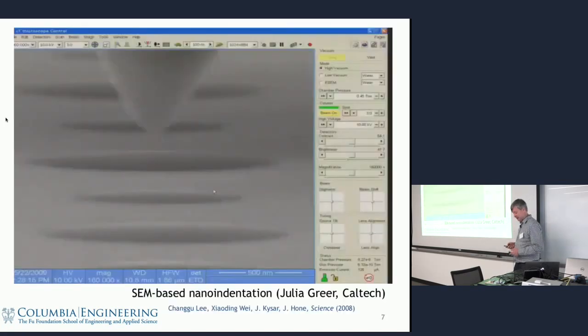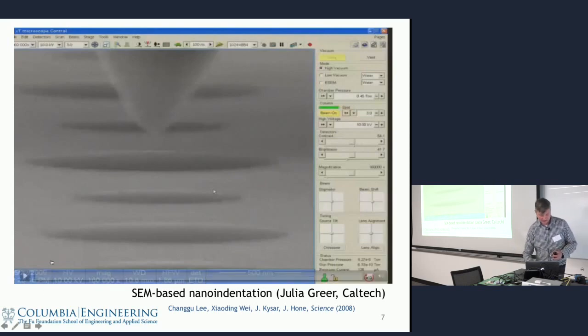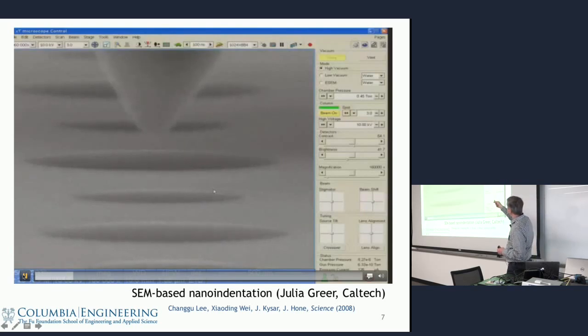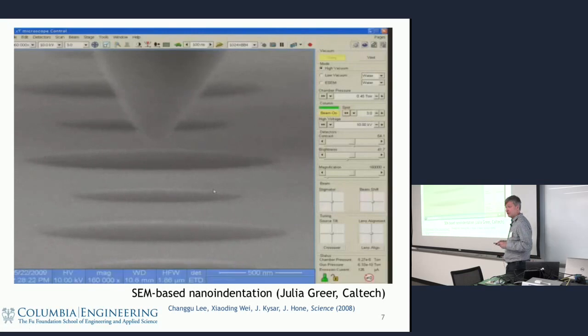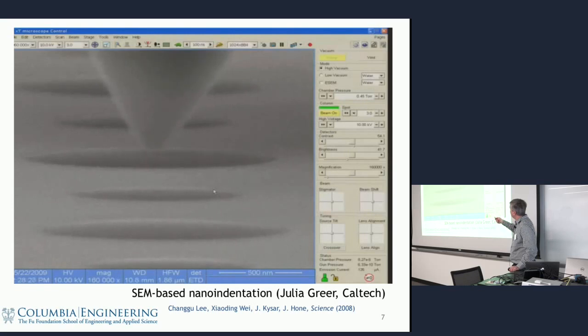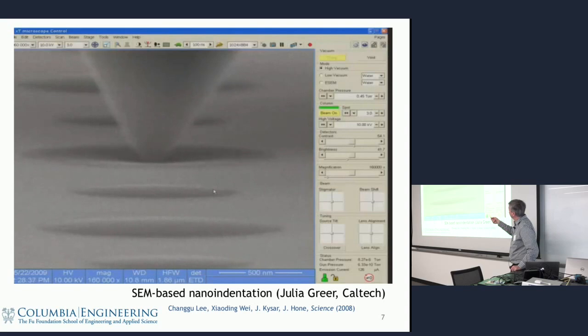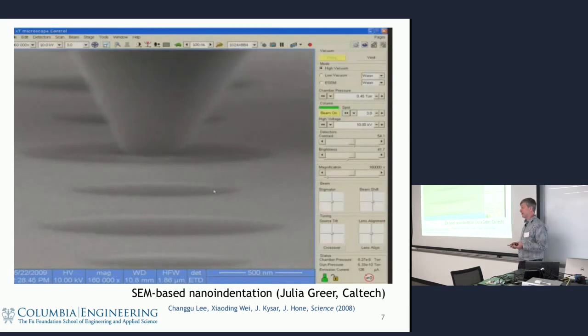So when we do these indentation tests, we get something that looks like this. So this is actually, we don't have a nice system like this. This is our friend Julia Greer at Caltech did this movie. But the idea is we come in with a tip. So this is a diamond tip. I'll talk about in the original experiments, we first started with conventional tips. This is some of these membranes, 1 and 1.5 micron in diameter, looked at from an angle, which is why they look elliptical. And you can see now we're starting to deflect. And there you go. And you can see this graphene is incredibly robust. You can really push the heck out of it. And then we see brittle fracture right at this point. Right? So this is the basic process we want to understand.